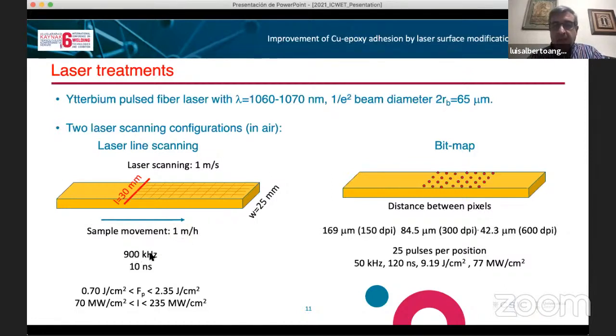We have been working with a pulse width of 10 nanoseconds, and we have been checking different fluence and irradiance values from 70 megawatts per centimeter square to 235 megawatts per centimeter square. Also, we have been working with a bitmap configuration in which the laser makes a network of dots on top of the sample, and we can control the distance between dots, and depending on this, we can control the resolution of the line or the drawing we are making.